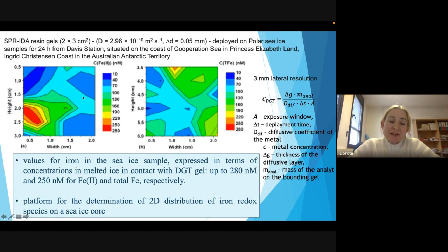So generally, we put the gels directly on the polar sea ice. We determined the distribution of iron in the melted ice that was in contact with our sampler and the probe. We found that the concentration of iron is up to 250 nanomolar, whether we are talking about iron(II) or the total iron.